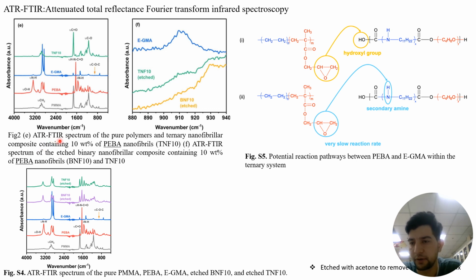So figure 2e shows the ATR-FTIR spectrum, in which some important absorption peaks are identified. Like in PMMA, the absorption peak at around 1723 is related to the ester carbonyl group, C=O. Other peaks are also related to CH2 and so on, but this is very important. Second, in PEBA, the amide I C=O stretching vibration, and it also shows stretching vibration of the ester carbonyl group.